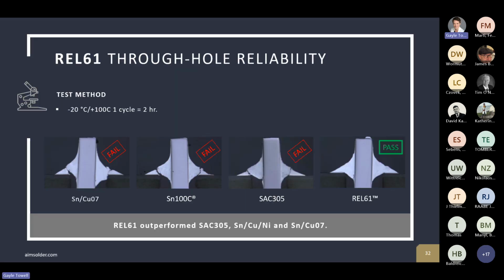Next, we're going to talk about through-hole reliability. So here we just see some images of joints, and the REL61 joint is performing very well with no cracks. This was a test that was done with thermal cycling between -20 Celsius and 100 Celsius. REL61 outperformed SAC305, tin copper nickel, and a tin copper alloy in this test.